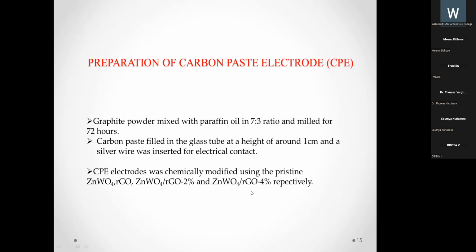Then for electrochemical sensing, we are using carbon-based electrodes for coating. We have prepared the carbon-based electrodes in our lab: the graphite powder is mixed with paraffin oil in a 7:3 ratio and ball milled for about 72 hours. The carbon paste so prepared was filled in a glass tube to a height of around 1 centimeter, and a silver wire was inserted for the electrical contact.